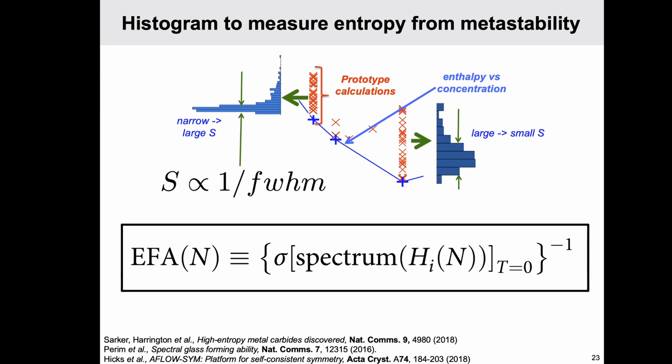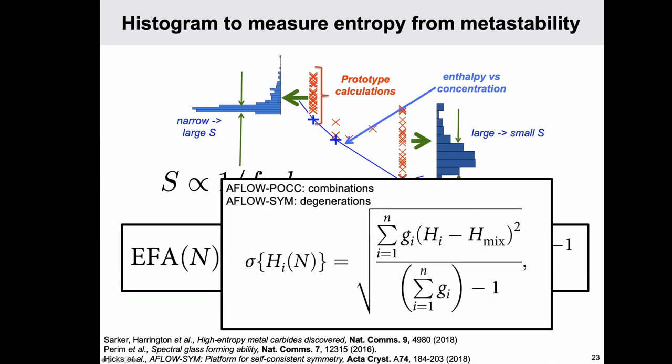Remember that there are some tricks here, because when you calculate these occupations, you also need to consider that there are a lot of phases that look the same. Okay, so look, they are the same, even if they don't look the same. So you need to calculate the symmetry, the factor group, which is the number of configurations that give the same unit cell. And therefore, in getting the real weights, you need to be careful, and you need to use these G's, which are the cardinality of the factor group with respect to the structures that you calculate with your quantum code.